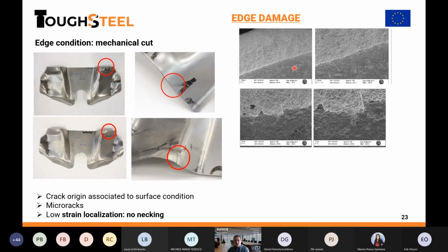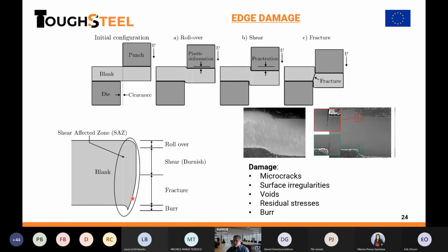But what happens if we cut it? This is the same part, but with a mechanical cut, and the situation is totally different. We have the crack origins associated with the surface conditions. It really starts at the surface. We see micro cracks, and we could see almost no strain localization, almost no necking. So the fracture is fast, localizing without necking. This is the characteristic of edge cracking. We should look at the edge damage then.